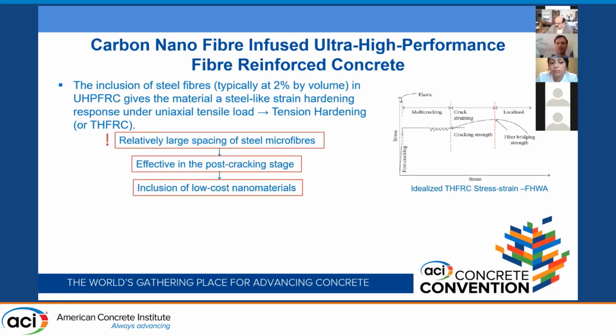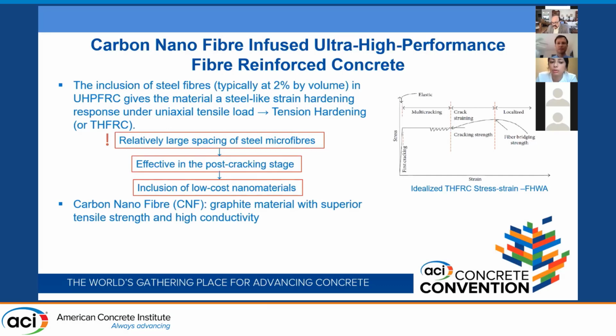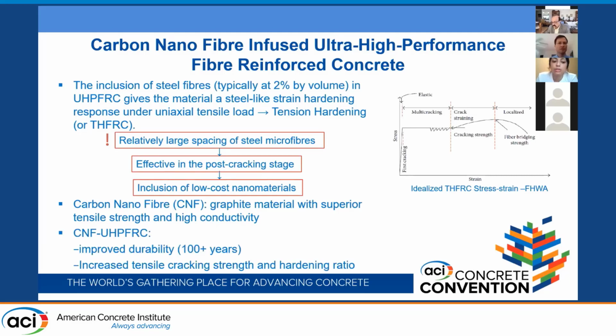As a result, the inclusion of a low-cost nanomaterial is introduced as a suggestion, and so come the carbon nanofibers. Carbon nanofibers are a graphite material with superior tensile strength and high conductivity. What does the carbon nanofiber do for the UHPFRC? It improves its durability to above 100 years, and most importantly, it increases the tensile cracking strength as well as the tensile hardening ratio.